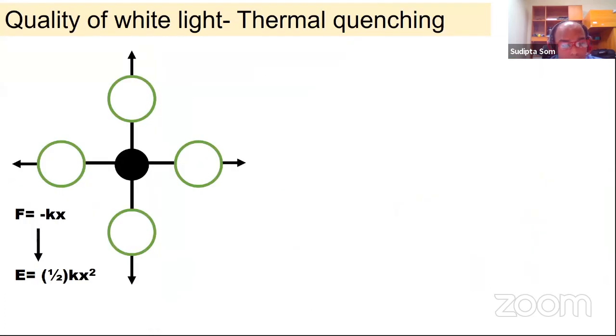So, however, the thermal quenching problem caused by the heat generated within LED chips results in disappointing reliability and lifetimes of high-power phosphor-converted LEDs, which is still a bottleneck limiting their practical development. To date, the maximum working temperature, as I discussed previously, is limited to below 120 degrees centigrade to ensure the quality of the luminescence output due to the deterioration of the phosphor above this temperature. Hence, thermal management has become a significant issue as well as a great challenge for the applications of high-powered LEDs.